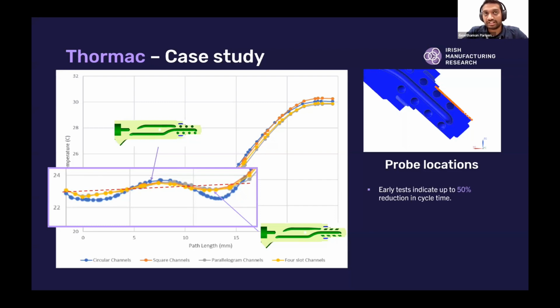Initially, the total cycle time was 32 seconds with 17 seconds of cooling time. And using the inserts with conformal cooling channels, the total cycle time was reduced to a little bit under 15 seconds, which in fact is lower than the initial cooling phase. So that's a really good reduction in time.